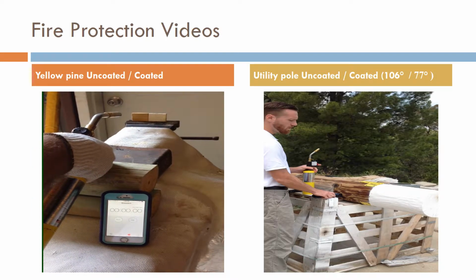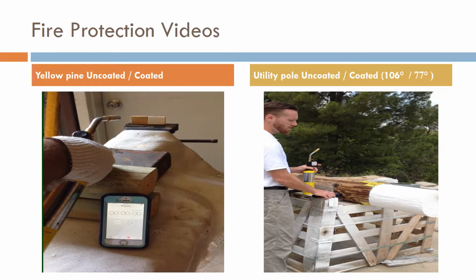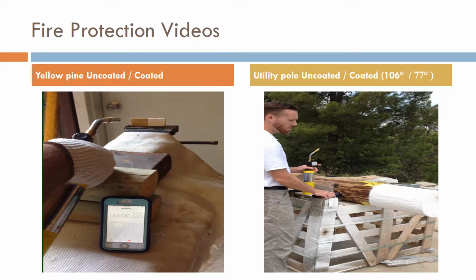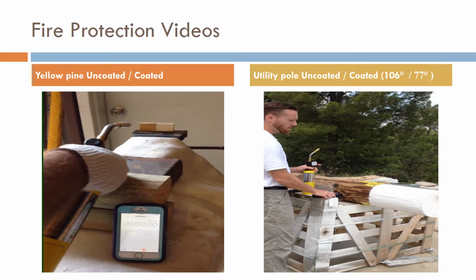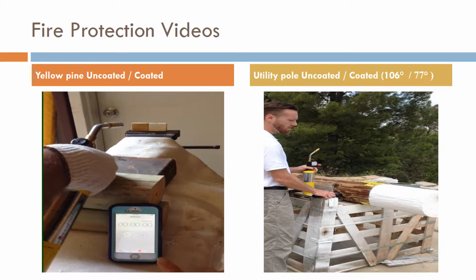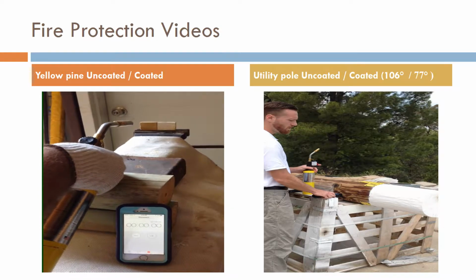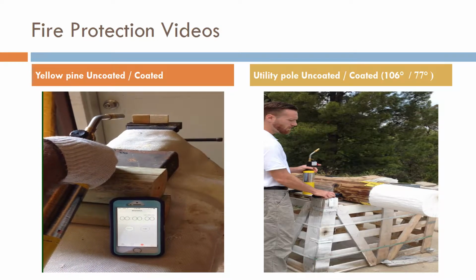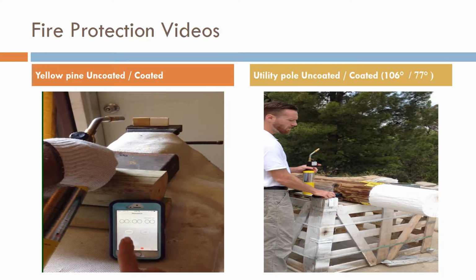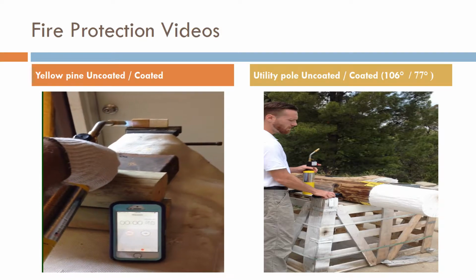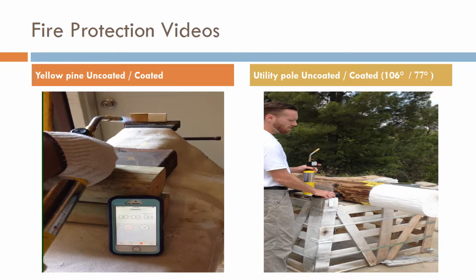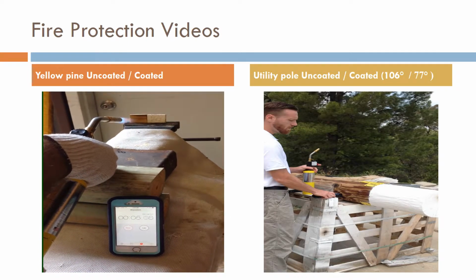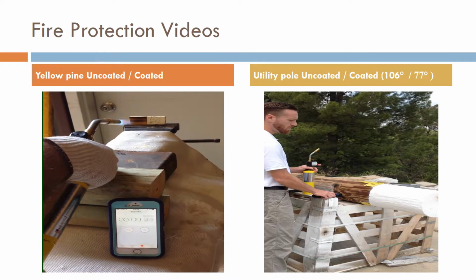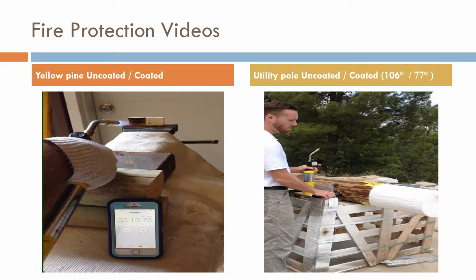Under ASTM E136, our coatings are rated as non-combustible, allowing us to automatically meet most ICC and IBC fire code requirements. In this video, a 3-minute burn test with a 3,000 degree MAP gas torch is done on a small block of coated and uncoated cedar building wood. You will see the uncoated sample immediately catches fire and ultimately burns completely through. The treated sample reacts to the heat and protects the wood underneath.